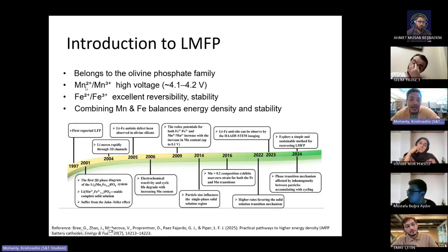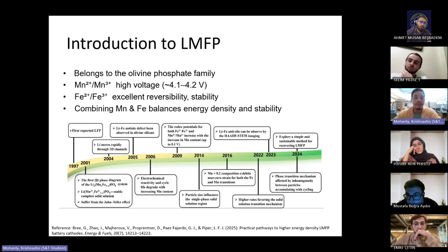And then why do we have to include manganese? Why can't we include any other element per se? Because there are a lot of elements that we could include in this case. So we pick manganese because its redox potential is higher than iron itself, which is able to generate more energy density. So for the same stability and the same structure, we can get a higher density, which can also improve our life cycle and the energy output per hour.